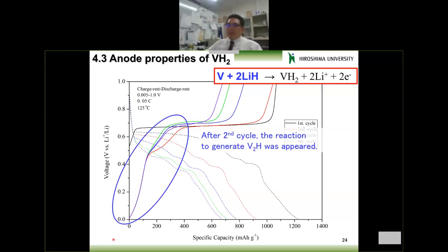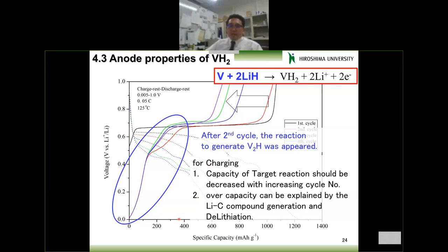So actually, we assumed this is due to carbon materials. And for the charging process, the capacity of the target reaction should decrease with increasing cycle number. And some overcapacity can be explained by the lithium carbon compound generation and delithiation.